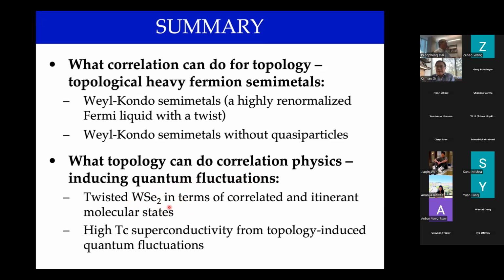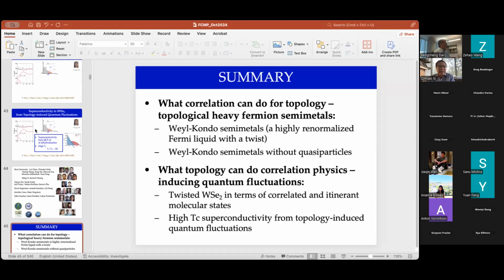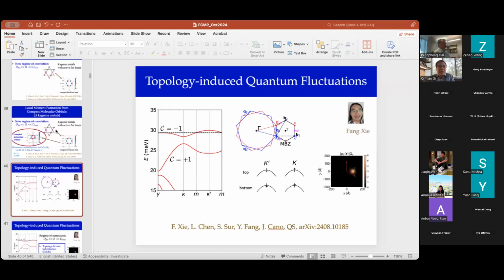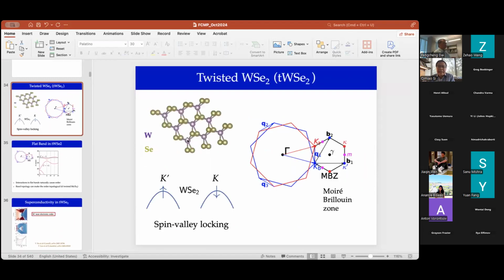Before anyone else asks, let me ask you for the case of the latest case. Do you think it's actually induced by, you said, correlation induced by magnetism, or is there no magnetism in the system, in twisted WSe2? Yeah. So the precise electronic order is interesting. Certainly, experimentally it has not been fully clarified. It's not ferromagnetic order based on experiment. There's also one aspect which I mentioned, that the structure and energetics is such that there's a valley-spin locking. So the valley degree of freedom and spin degree of freedom are locked, mixed up in this system. So even if it's an antiferromagnetic order, it's not conventional antiferromagnetic order. Could show up. I see.